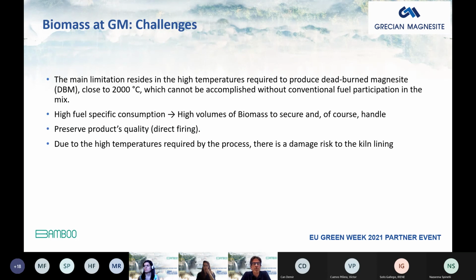There is also, as I mentioned, the high specific fuel consumption, which means that we have to secure high volumes of biomass and, of course, handle it, making sure that the product quality is preserved. I mentioned the direct firing mode: the flue gases and the ash from the biomass will come into contact with the raw material and the product. And of course, due to the high temperatures required by the process and the generation of ash, there is damage risk to the kiln internal lining.